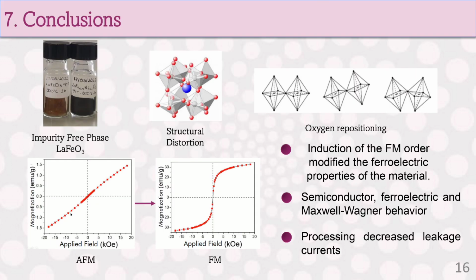In conclusion, it was possible to synthesize lanthanum ferrite without impurities. There was a structural distortion, including a rearrangement of oxygens that had an impact on the change of magnetic order from antiferro to ferromagnetic. The induction of the FM order modified the ferroelectric properties of the material: semiconducting, ferroelectric and Maxwell-Wagner behavior. The chemical composition was congruent with lanthanum ferrite and showed that there is adsorbed oxygen related to vacancy generation as a charge compensation mechanism to maintain the neutrality of the material.